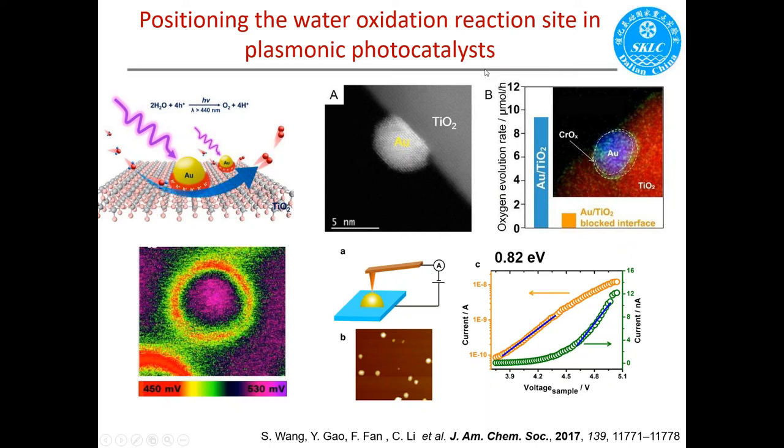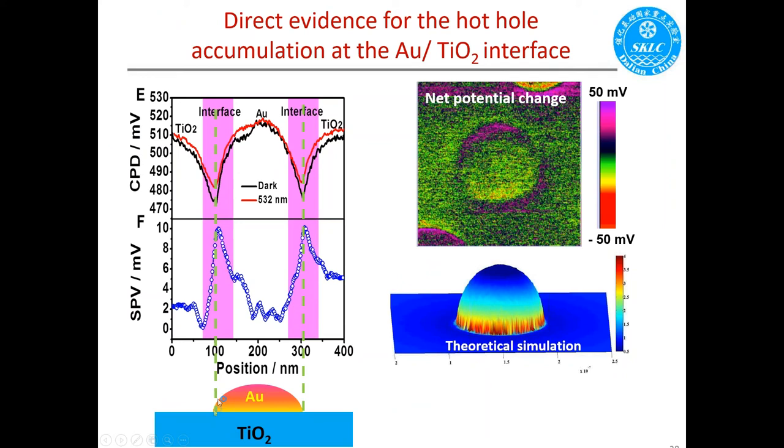The most important thing is that we detect the hole signals at the perimeter of this gold and titanium oxide at the interface. You see that we can give you a hole signal according to SPV spectroscopy. If you make an image, you see that most of the photogenerated holes are at the interface of gold and titanium. So it agrees well with the theoretical simulation of the distribution of the localized